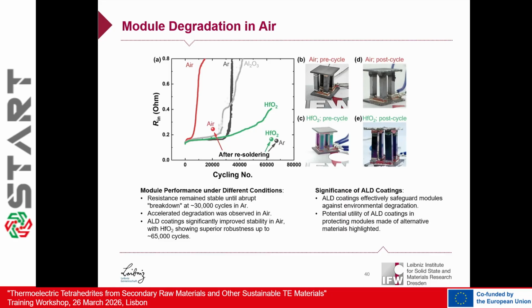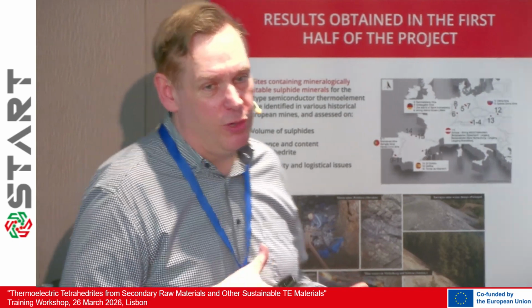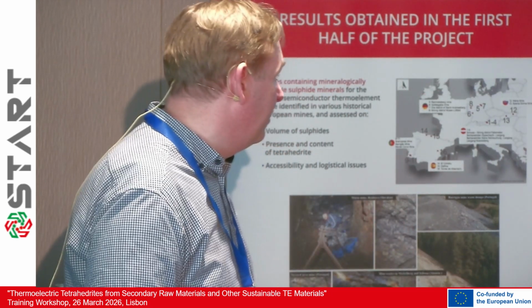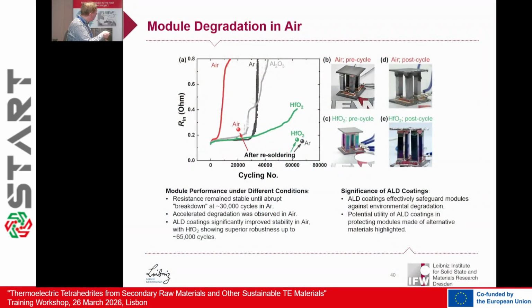If you put aluminum oxide on it, it works a bit better for a longer time, but aluminum oxide forms with magnesium a rather easily water-soluble oxide, and this also does not really protect our module. Therefore, you should use a more robust oxide, like silicon oxide and hafnium oxide. If we cycle this whole module for half a year, it's rather stable. What we have figured out is that the weakest point is the soldering.